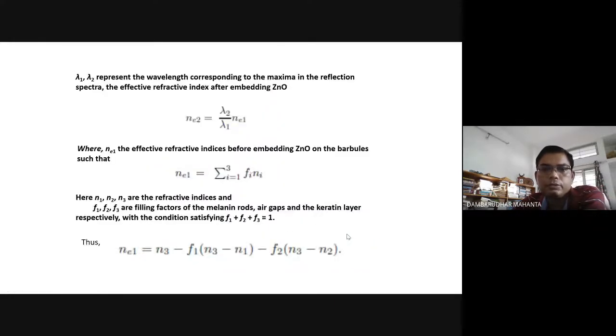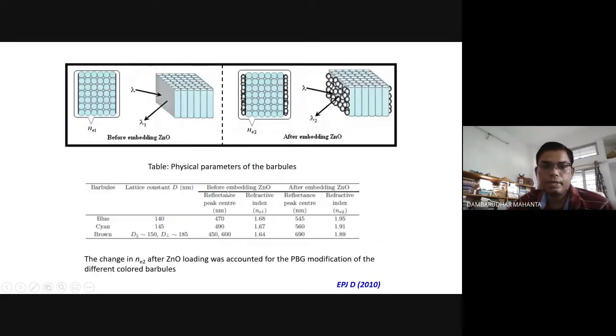So the formula has been used like this: modified refractive index is equal to lambda 2 by lambda 1 into the previous refractive index. And accordingly, the filling factor also we considered for melanin rods, air gaps, and keratin layer, because the total space was filled by these three materials. You have melanin rods which exist, and they are separated by air gaps and keratin. So that is why the whole thing will be equal to 1. So with this formulation, one can obtain these values.